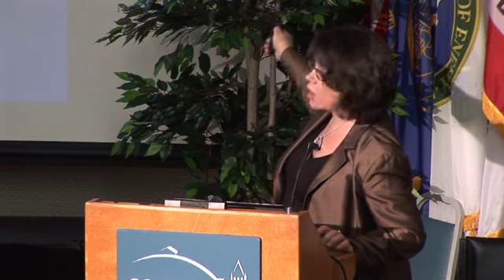No, it's not. But the fact is that this rate of decay really drops off dramatically as you keep cycling, because now you start to precipitate things on the positive and negative electrodes. So that capacity fade becomes almost self-limiting. After a certain point, it stops, because once those layers build up, they don't build up anymore. So the problem can be addressed by interfaces at the positive and negative electrode. And that's what we are working on now, which is why I would say that I'll tell you in 2 years.